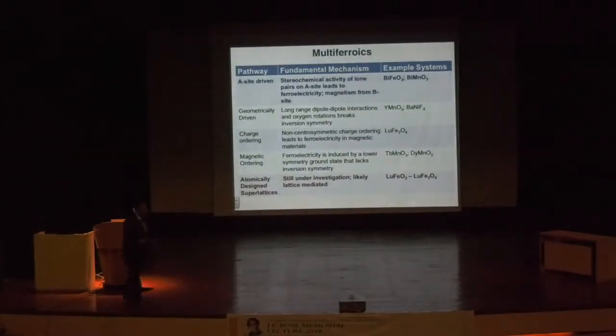Okay. So I could design them by taking the A site in this perovskite structure and making it bismuth, which has a large 6s electron contribution, so you get a very large polarization from that. And you can put the magnetism into the B site, in this case iron. Typically, these are super exchange coupled, therefore they're antiferromagnetic. Okay. And that's a big question that we're going to deal with.